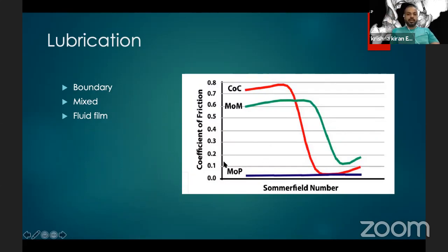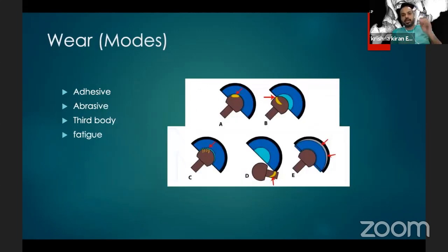But if you have a metal and poly type of articulation, we have patterns of mixed and boundary lubrication, where there is an incomplete or absent fluid film between the opposing surfaces. And if you remember, I told you the entire surface is not actually in contact. It's only the asperities which are in contact. So this particular principle must be borne in mind when we make a choice of the bearing.